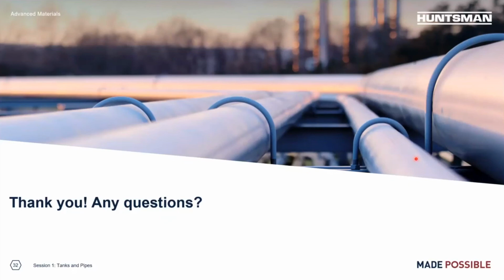Okay, thank you. Next one is, do we have to change stoichiometry when we use 2950? Yes, when we're using accelerator 2950, it has a mean functionality of about 75, and it depends on your formulation design. If we're using only a very minimal amount, for example only like 0.5, which will also improve your reaction speed, the impact on the epoxy and amine ratio is very minimal, so you don't have to change.